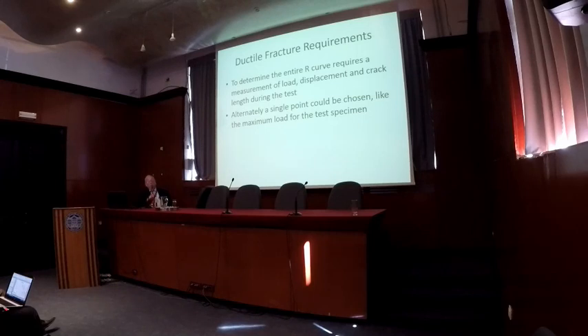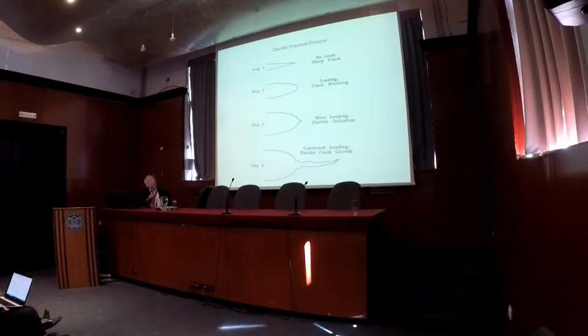So to determine an R curve, you have to measure load and displacement like you do in linear elastic behavior, but that's not enough. You have to have a measure of crack length during the test. Here's a schematic of ductile fracture: in the beginning of the test, a sharp crack before you've loaded. As you load, you get crack tip blunting, which is a geometrical extension of the crack, and then eventually you get the sharp crack extending from the blunted crack, which grows continuously. You don't get re-blunting, but this grows continuously.